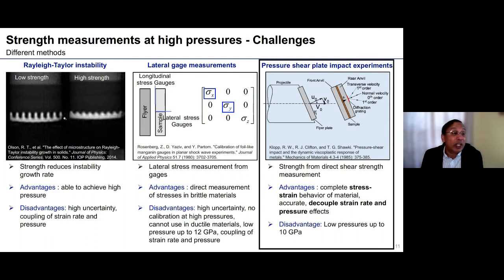As you shock the material, if the material is strong, or the strength is high, then the ripple growth will be small. If the material is weak, or the strength is low, then the ripple growth will be high. So this gives you a qualitative measure of the strength of the material, and obviously one can do numerical simulations of the instability growth, and then achieve high pressures and obtain the strength. But at the same time there is high uncertainty in the coupling of strain rate and pressure, because as you can imagine, in this ripple growth the strain rate and pressures vary and are spatially non-uniform.